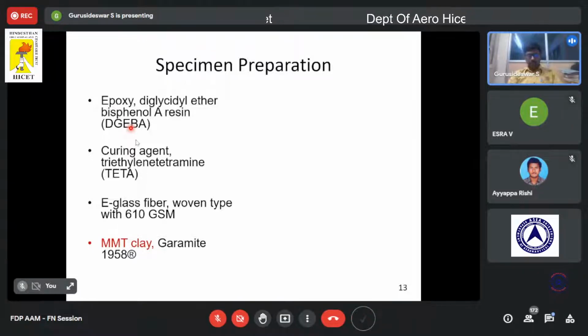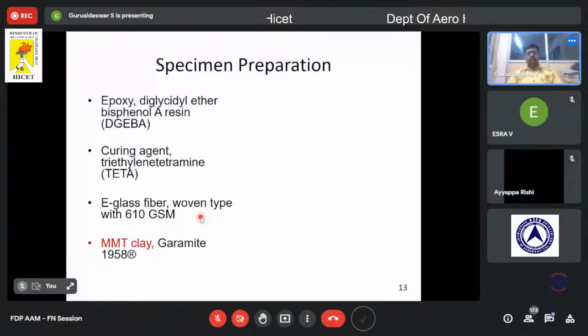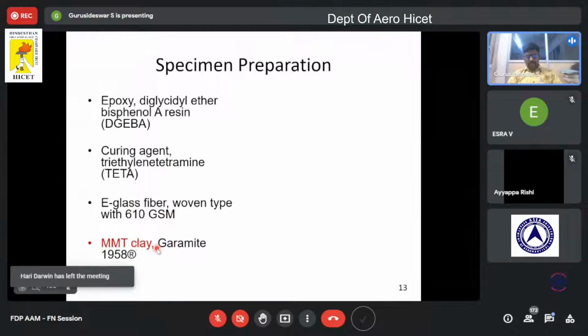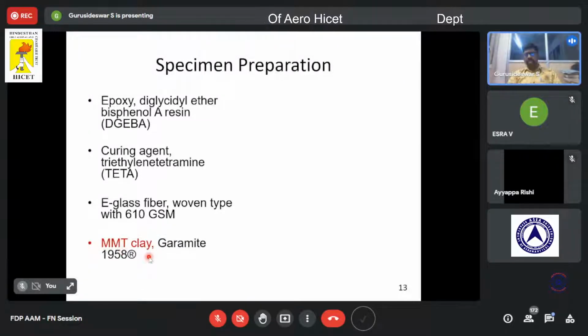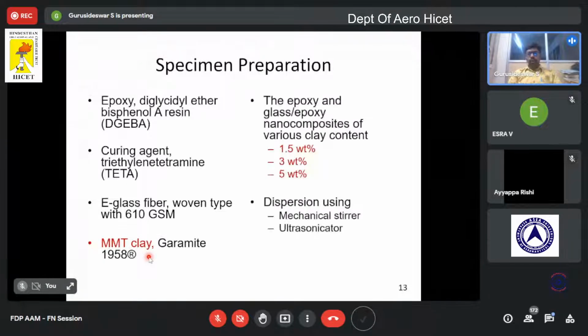And the second one, we are going to disperse the clay in a traditional composite, like a traditional FRP composite. So we have used an E-glass fiber, which is commercially available. It's a woven type fiber. It has 610 GSM, grams per square meter. So this is the primary reinforcement, and we add clay as a secondary reinforcement. So as I told earlier, we used modified montmorillonite clay, and the commercial name is Garamite 1958, which was supplied by Southern Clay Products, USA.